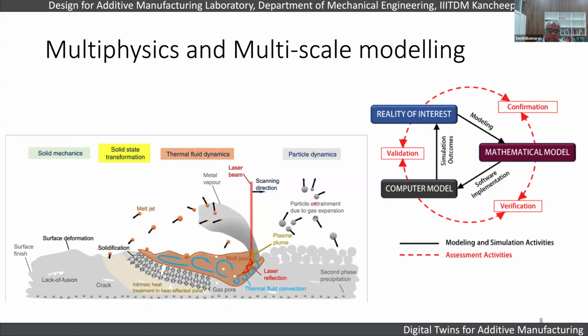And then the particle entrainment due to gas expansion, and you can get a plasma plume. This is the direction in which the laser is scanning. This is the powder, and this is the complete melt zone. You can see there's a lack of fusion, cracks, and porosity. And this is the melt pool, which has a